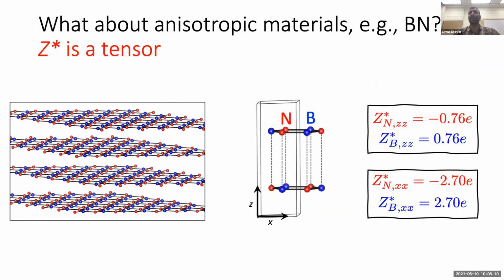And then the other thing that I will just remind you about Born effective charges that makes them different from static charges is that the Born effective charges are a tensor, not just a scalar. So we can see this in an example of a very anisotropic material. This is two-dimensional hexagonal boron nitride. So we have these layers of boron nitride that are bonded strongly in plane and then very weakly out of plane. And if we calculate the Born effective charges for the different sublattices of this material, we get very different results if we consider the electric field and the response along the z-axis, perpendicular to the plane or parallel to the plane. So perpendicular, it's something like 0.76 electrons. Parallel to the plane, it's closer to the nominal ionic charges you would expect for boron nitride, plus and minus 2.7.